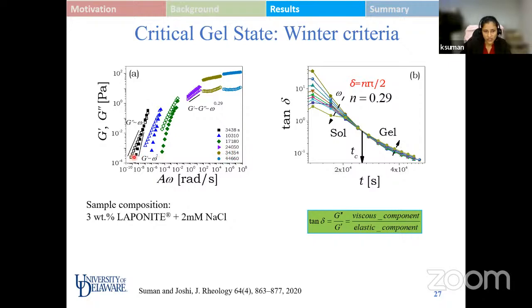We can see that initially, at lower times, we have liquid-like behavior shown by the terminal scaling. With increase in time, at a particular time, we have identical power law behavior of both the moduli. So this time can be characterized as the critical gelation time of the laponite dispersion studied in this work. Also, the corresponding tan delta evolution is shown on the right, and we can see that at the identical time, the tan delta curves corresponding to different frequencies become independent of the applied frequency, which leads to the estimation of the critical gelation time.